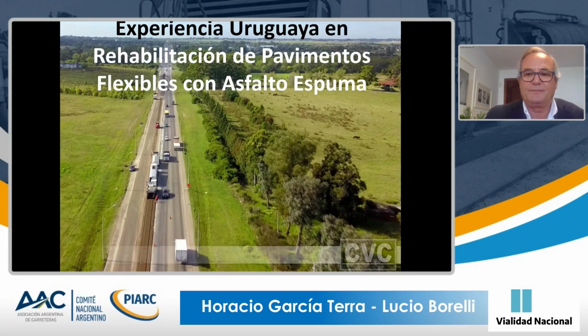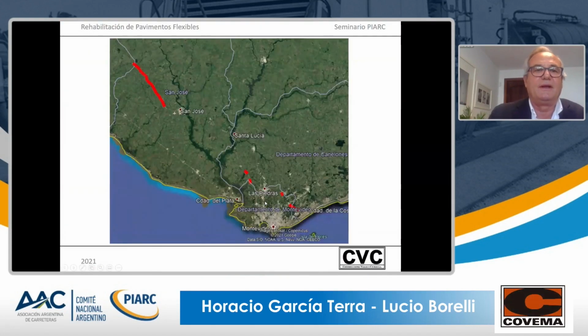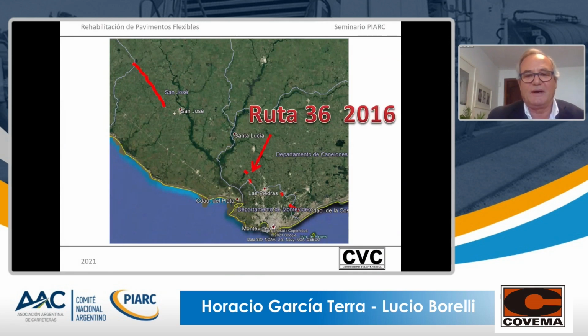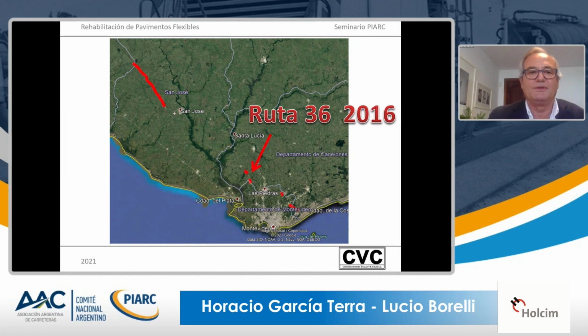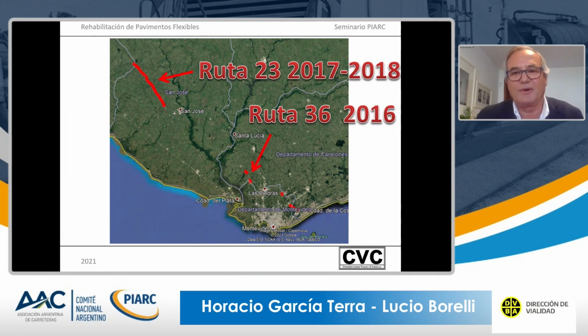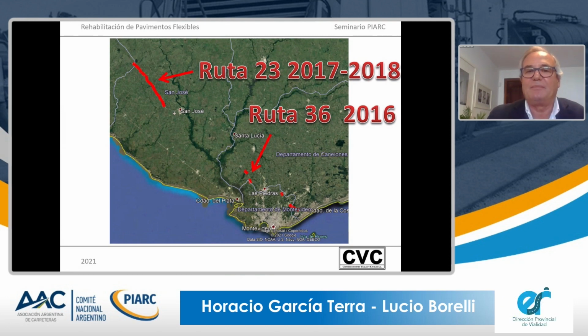The experience in Uruguay started in 2016 in Route 36. We rehabilitated several stretches in a highly deteriorated road. And in 2017-2018, we also started rehabilitation, and we had to stop during winter time because the foam asphalt technique must be applied with over 15 degrees centigrade.